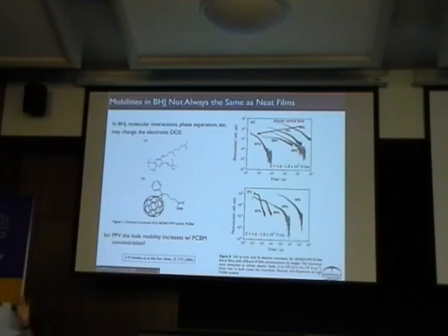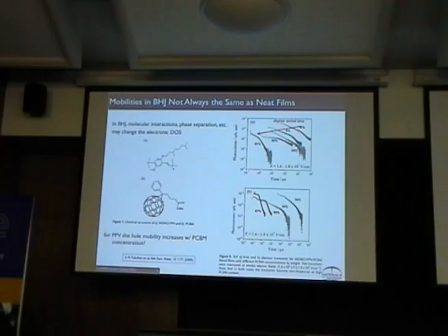The thing to remember is you can do time-of-flight experiments for a pure material — just one material. If you did the time of flight on those two materials separately, you might expect that tells you the hole mobility in the blend. Well, unfortunately no. Here's a classic example — this is some odd data that people still argue about. If you mix a material like PPV and fullerene and do a time-of-flight experiment, what you find is that the hole mobility of the PPV actually increases as you add more fullerene.